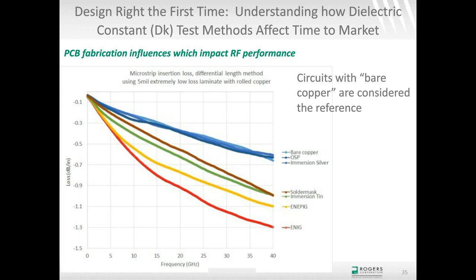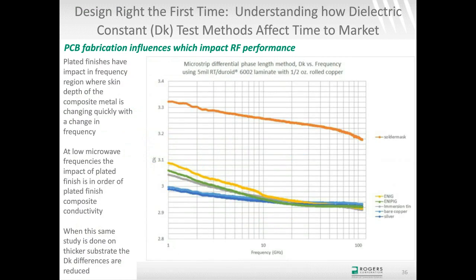So this is also from the same study. In this case, what I'm doing is using the microstrip differential phase length method to look at phase response differences. And in this case, I extracted the dielectric constant from that measurement. Dielectric constant on the left, frequency on the x-axis. And what we find is at lower frequencies, we see some differences in how the circuits behave for phase response. And what's interesting is they are in the order of conductivity, composite conductivity.